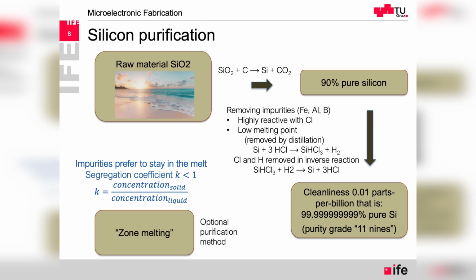Later, of course, we might want to add, for example, boron as doping, but in controlled and localized amounts. Thanks to the fact that chlorine is highly reactive with those elements, there will be compounds forming with iron, aluminum, boron, for example, which have a lower melting point than silicon and can be easily removed by distillation. In this distillation we are also forming a new silicon compound, from which the chlorine and hydrogen are removed by inverse reaction. And through this complex chemical process, we are achieving very clean silicon.